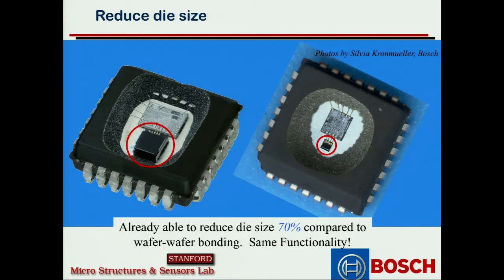We basically made a device that had exactly the same micromechanical structure as the Bosch production gyroscope of that time. We made it in this process, so it didn't need all of the wasted real estate of the bond ring, and it was substantially smaller. Had all the other same properties. In fact, from an electric test perspective, you couldn't tell them apart. So we thought this was terrific. Bosch was less interested, sadly.